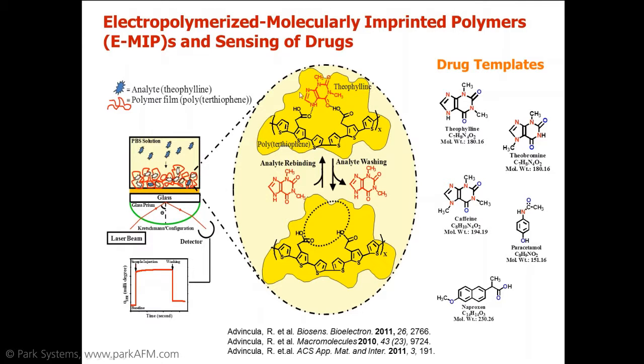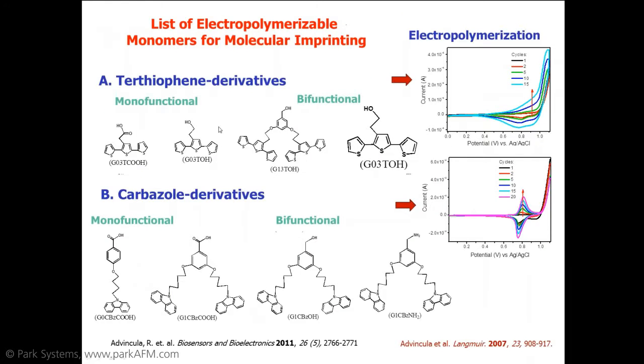In other words, not only theophylline as illustrated here, we can have a sensor for theophylline, a sensor for theobromine, a sensor for caffeine, paracetamol, and naproxen, and so on. And that will be very specific to this template that was used, which I'll show you in the next few slides. Here is a survey of the different monomers we used, from thiophene to bifunctional thiophene to bifunctional carbazole, and that's shown here. We can even have a second generation carbazole dendron.